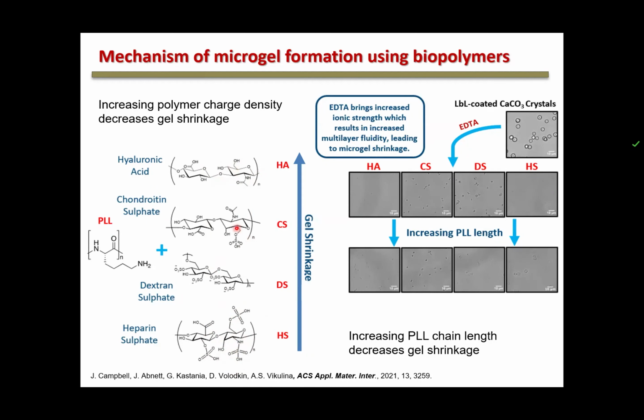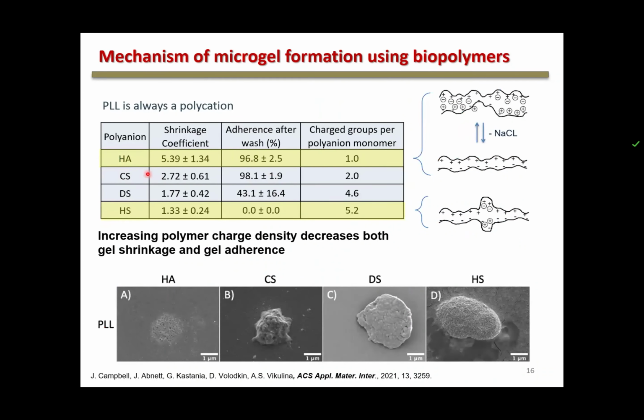And what we found is that if you increase charge density, this results in decreasing the shrinkage of microgels, so they shrink less, and this results in less adhesion as well. So adhesion and shrinkage of microgels, they work hand in hand. If they shrink, they will definitely adhere. If they don't shrink, there is a high chance they won't adhere. So here you can see some images of this. So here in this table, you can see those polyanions that have been used, and shrinkage coefficient goes from quite high down to rather low, and adherence also very high for highly shrunk microgels, and 0 adherence for microgels which nearly show no shrinkage.